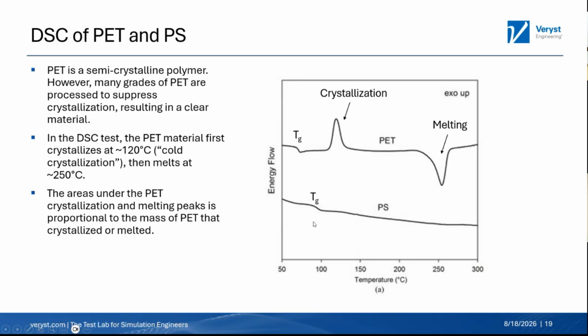In contrast, and this is where I want to talk about PET a little bit more, there's a lot more to be seen on this curve. You can see the Tg is actually a bit of a stronger signal for this material, but then there are two peaks. There's a positive peak here, which I've labeled as crystallization, and a negative peak here that I've labeled as melting. So what's happening here is that